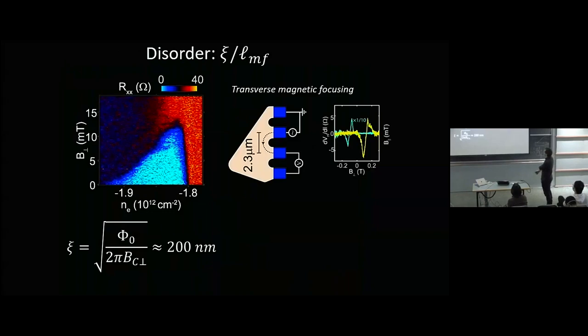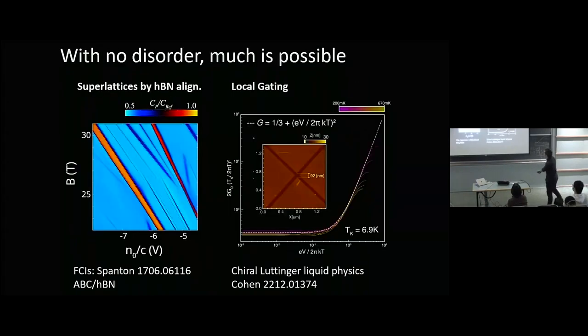So, hold on, before I go on to the details of superconductivity and so on, I just want to point out that with no disorder, you really have a lot of possibilities. That's kind of the theme of this talk, right? So some years ago, you can certainly put a superlattice back without introducing much disorder. In particular, by adding hexagonal boron nitride that's aligned, you can bring back a superlattice potential, which can give you things like insulators at finite density.